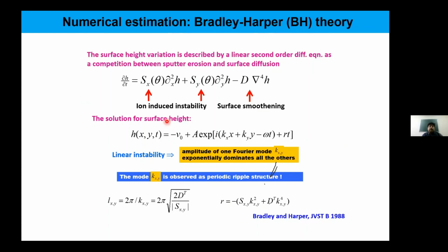So this is the ion-induced instability related term along the x and y direction. Sx, Sy is the sputtering coefficient along x and y direction, respectively. And this term corresponds to the surface smoothing due to ion-induced diffusion. And the solution for the surface height is this. So the amplitude of one Fourier mode, kxy, can exponentially dominate all the others.